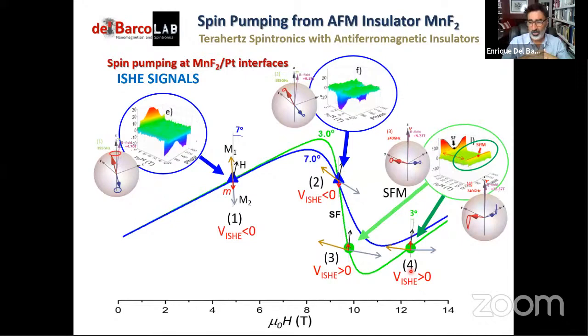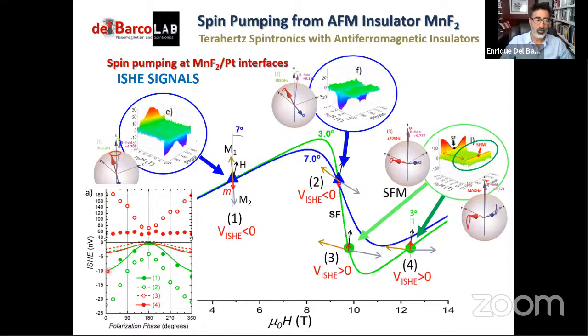But as I said, actually, we try to run calculations with the standard theory, the formal theory that I described before. We can fit this very well, for example, but if we fit this with the same parameters, we will be actually very far from fitting the rest of the observations. Those dots here, this data here is basically the height of these curves, right, for different polarization of the microwaves.